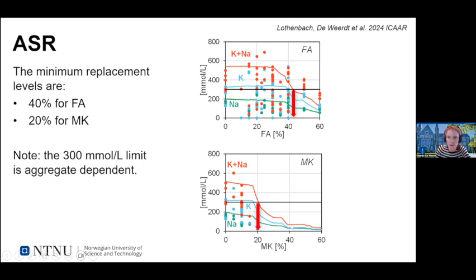I did it for fly ash and metakaolin. You see also some points here. This is experimental data we found in literature. So the green line is for the sodium concentration, the blue for potassium, and the red line for sodium and potassium concentration in the pore solution as a function of your replacement level. And we assumed a limit of 300 millimole per liter, so it's the slightly thicker black line here.